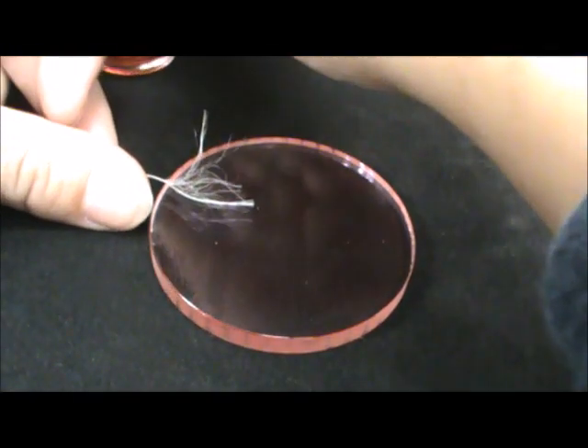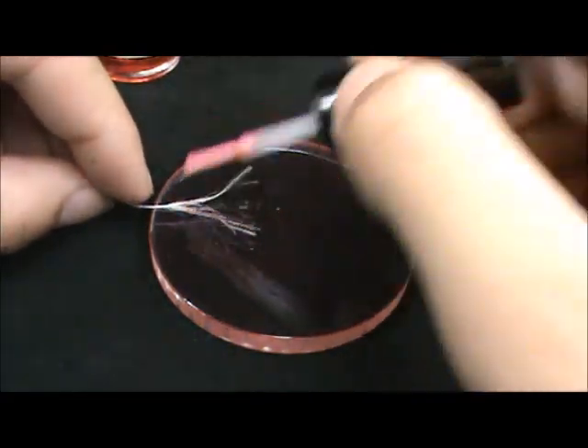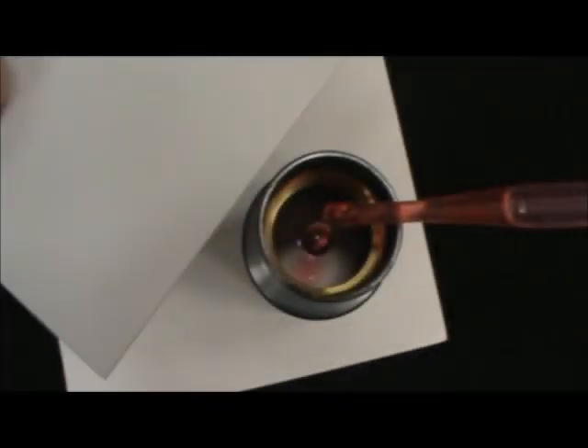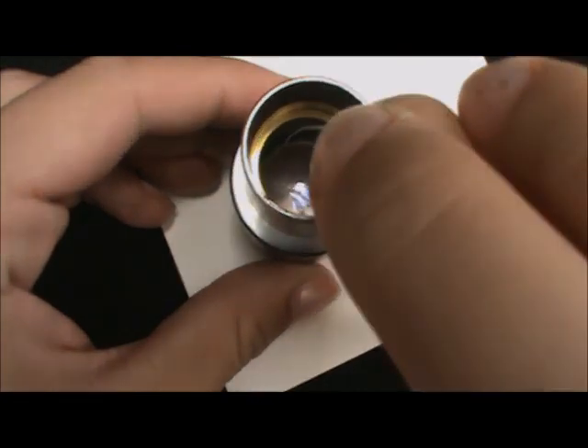Please note, on this optic, there's already been a layer of polymer applied. Floss is used to create a handle to remove dried polymer. Apply the polymer, allow to dry for a few minutes, place the floss down, and add a few drops of polymer to glue it down. Do not put floss directly on an optic, then apply polymer. It can leave a thin layer of residual polymer when removed.